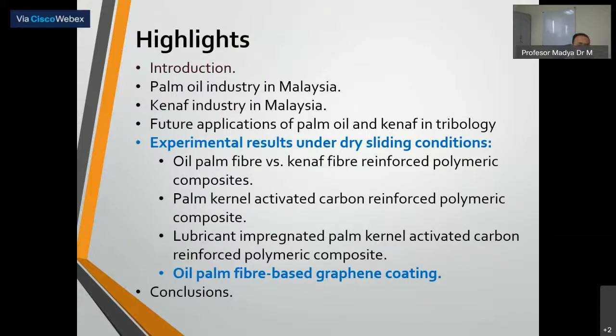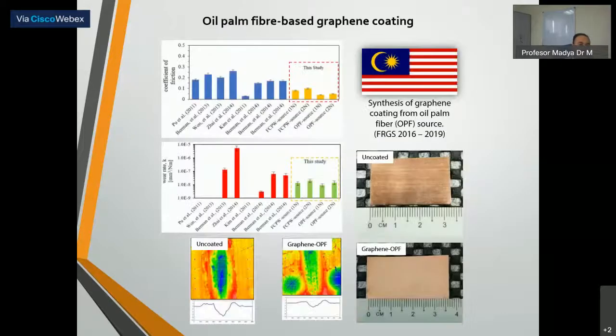Okay, now we see the oil palm fiber based graphene coating. This is actually our latest research, our latest finding. We use the oil palm fiber as the carbon feedstock for the graphene coating. This is the graphene coating on the copper substrate, and we use the CVD method. CVD means chemical vapor deposition method, and then we successfully grow the graphene on the copper substrate.